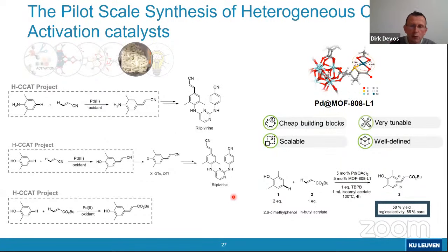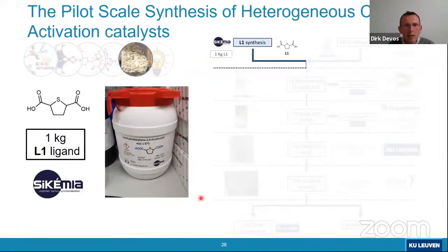I'm not going to give the full account of this, but what I really wanted to show to you is that even if you think that this is an exotic catalyst, we actually were successful in doing this at pilot scale. Why? Because all the compounds that we use, the MOF, but also, for instance, this linker molecule, this ligand that we functionalize the MOF with, are actually cheap and easy to synthesize at large scale also. For instance, if you think about this tetrahydrothiophene, it's actually very easy to synthesize, starting just from 2,5-dibromo adipic acid. So if you just have adipic acid with bromine substituents on positions 2 and 5, it's very easy to convert that to this tetrahydrothiophene, which can then be directly used.